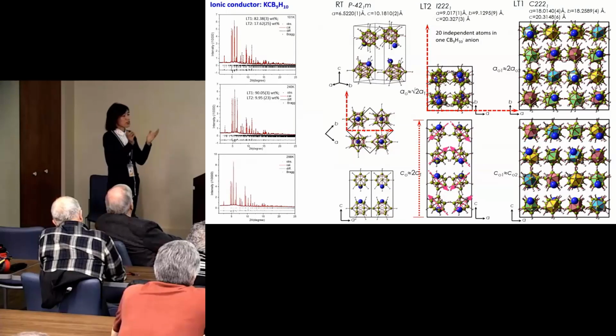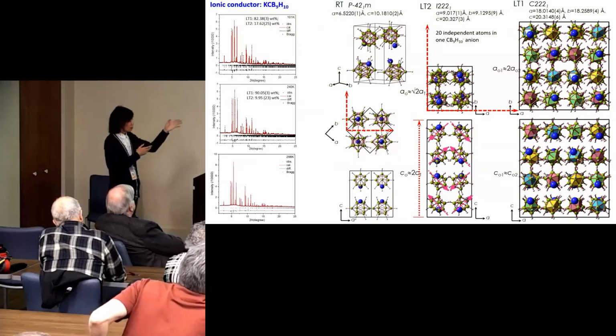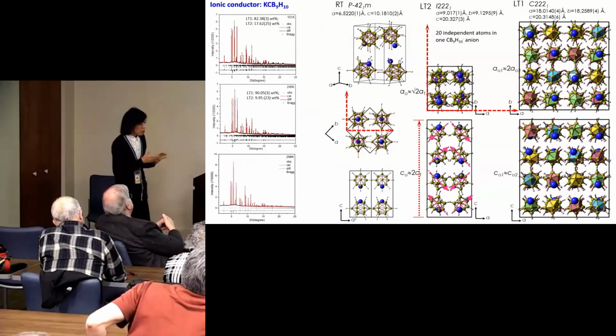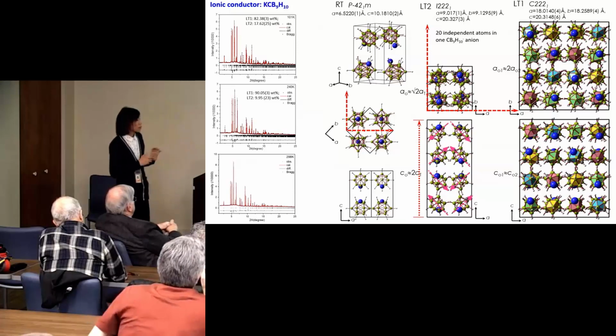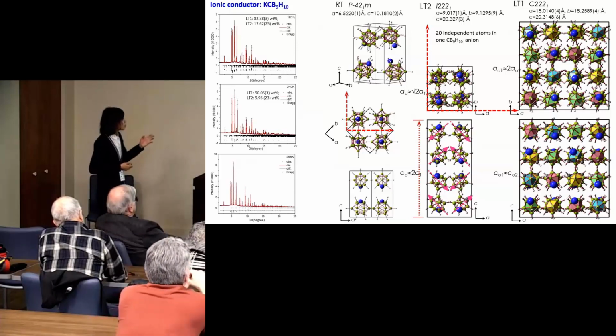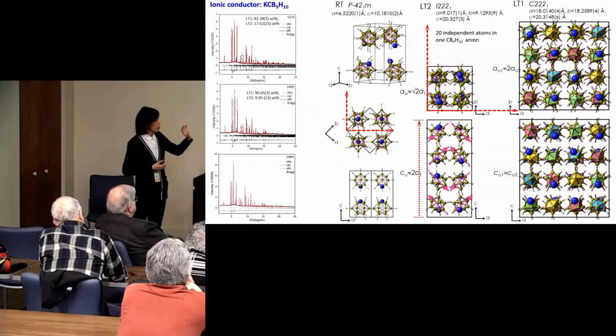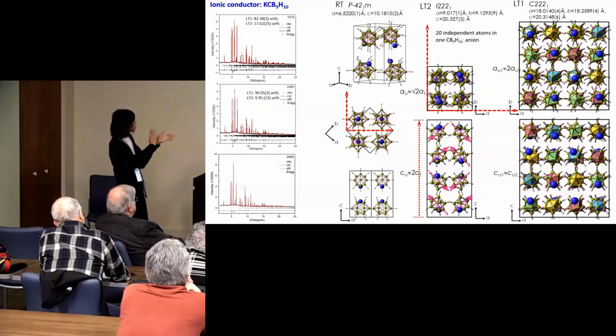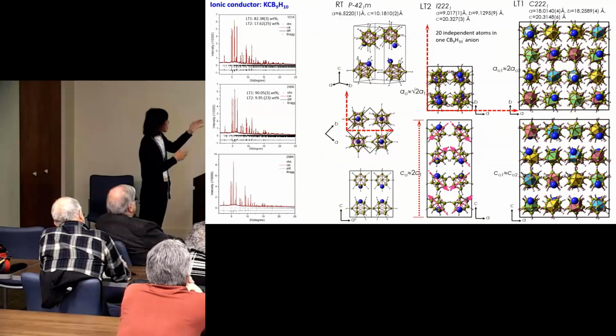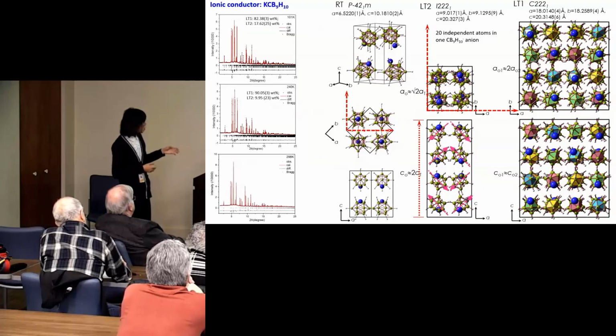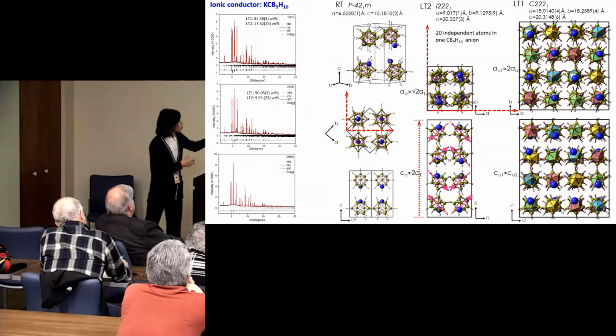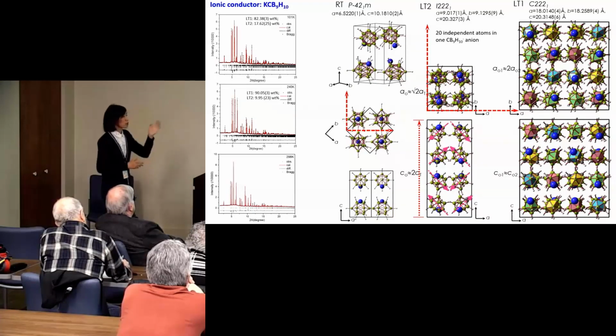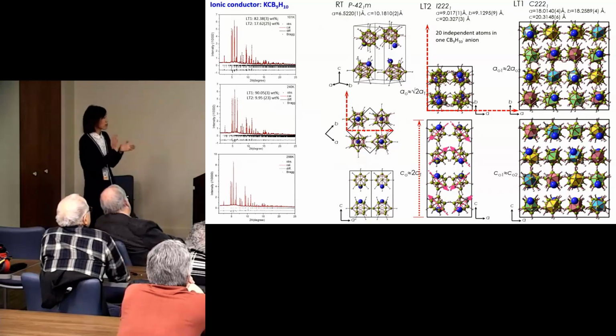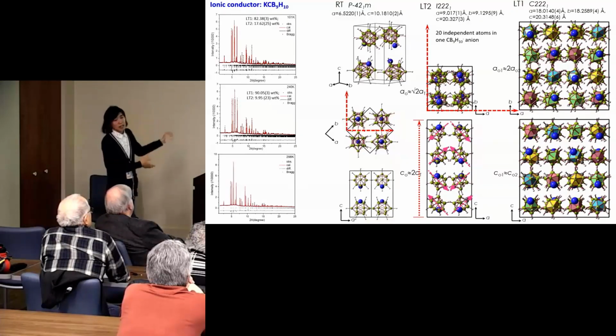It forms a disordered structure, just like the example I just showed you, sodium B10H10. It forms an FCC-type close packing. And then at room temperature, it forms an ordered structure with definite orientation of the CB9H10 ions. And upon further cooling, it will convert to two low temperature phases. And those phases always stay together, even down to the base temperature.